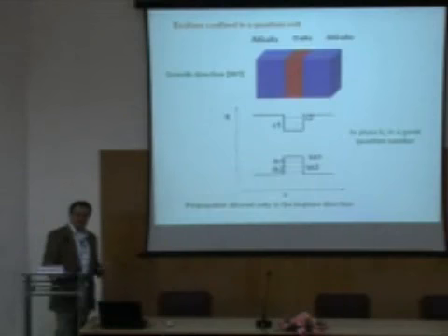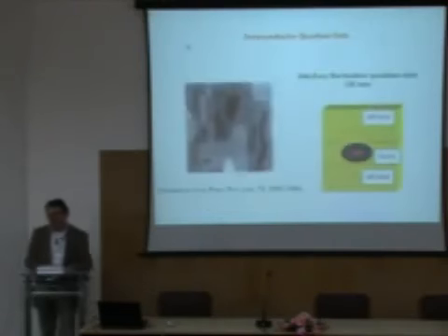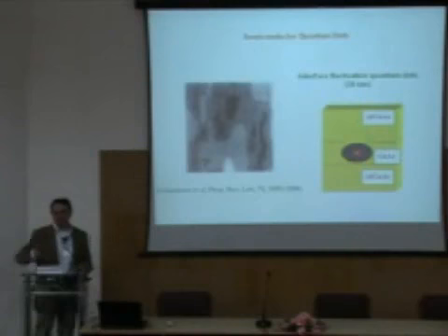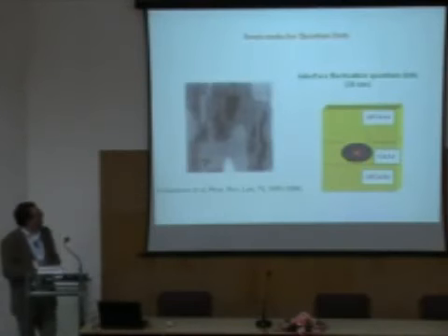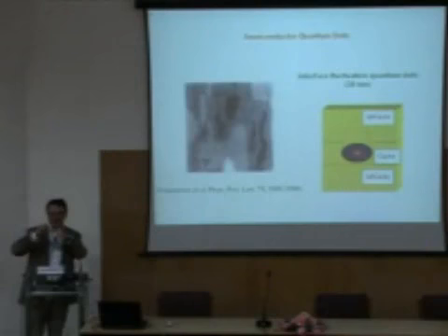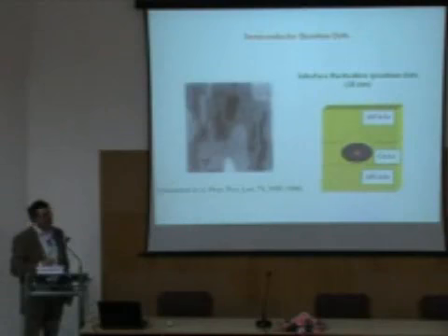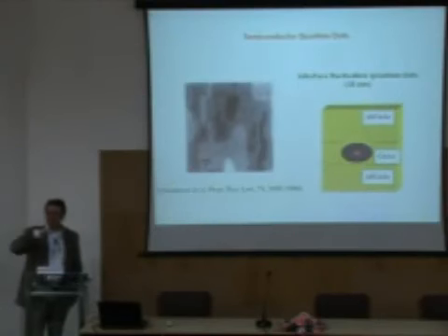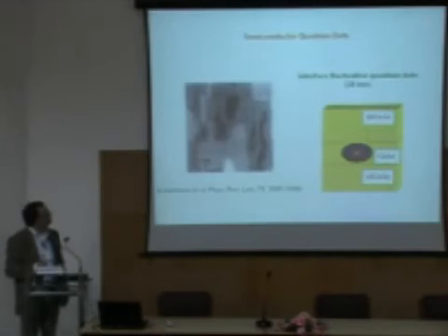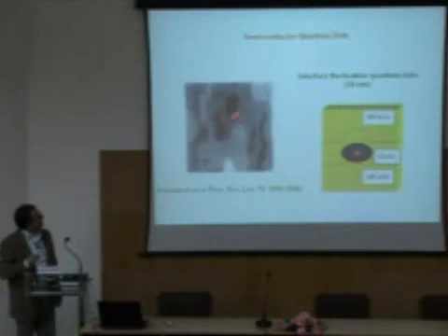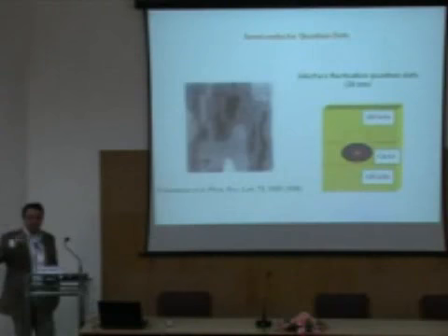Actually, I'm talking about quantum wells because the easiest way to make a quantum dot is just to take a bad quantum well. Okay. So you try to grow a quantum well, and you do it too fast, very fast. And what happens is that at the interface between the material that makes the well and the barrier, you will have fluctuations in the number of atomic planes that are deposited in this structure. This deposition is called MBE deposition. So here, for instance, this island here, you have a larger number of atomic planes in the quantum well.